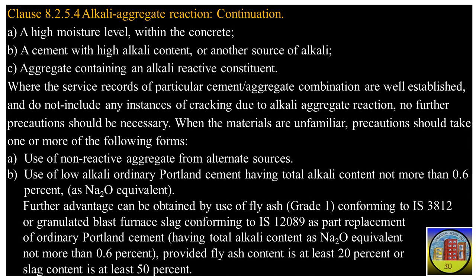When the materials are unfamiliar, precautions should take one or more of the following forms. A. Use of non-reactive aggregate from alternate sources. B. Use of low alkali ordinary Portland cement having total alkali content not more than 0.6%, as Na2O equivalent. Further advantage can be obtained by use of fly ash, grade 1, conforming to IS 3812, or granulated blast furnace slag conforming to IS 12089 as part replacement of ordinary Portland cement, having total alkali content as Na2O equivalent not more than 0.6%, provided fly ash content is at least 20% or slag content is at least 50%.